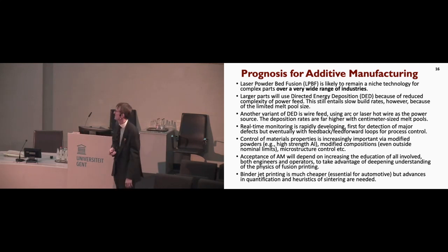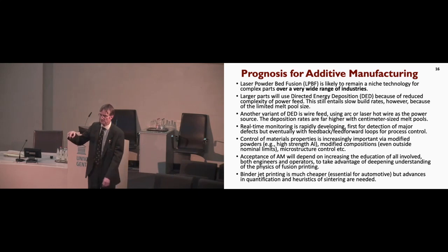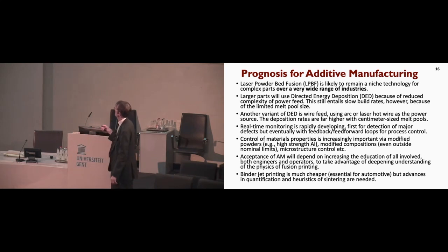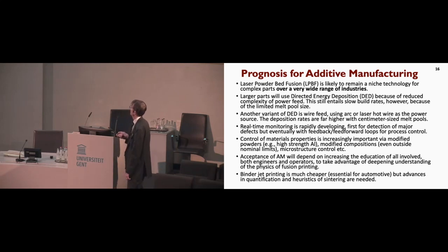However, having said that, if you want to build larger parts, we're going to have to use directed energy deposition. Now, most of us know this via feeding powder into the melt pool. But another very important variant is the wire feed approach. And this was originally only available with electron beam melting, which had its inconveniences, like very large vacuum chambers. But now you can do this with wire arc or laser hot wire machines. And it works. It demonstrably works. Of course, you're going to have to expect to do more machining of the parts that you get from that. Real-time monitoring is developing really fairly quickly.